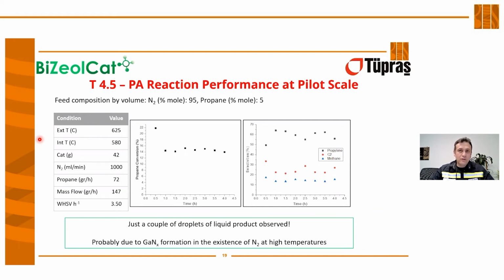This reaction is actually validated in the lab with argon, not with nitrogen. But of course, it's very difficult to find argon in an industrial environment. Therefore, we first started with nitrogen in order to see its effect in this reaction at pilot scale. Of course, we obtained almost nothing, just a couple of droplets of liquid product observed in the chiller section of the collection vessel. Therefore, we decided to go to the argon flow with the same WHSV values.